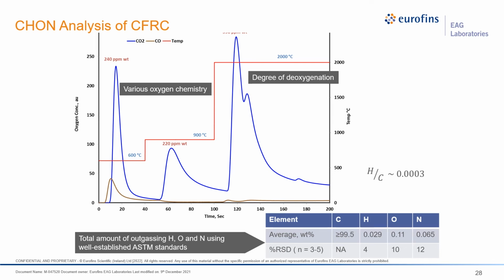On this plot, oxygen concentration in composite is compared with heating time and temperature. The distinct outgassing profiles observed for carbon monoxide and carbon dioxide, two main oxygen-containing species, clearly show presence of different oxygen chemistries and also provide guideline on how deoxygenation occurs for this composite. The table gives concentration of carbon, hydrogen, oxygen, and nitrogen measured using calibration performed by analyzing NIST traceable oxygen standards and also by using ASTM methods. As you can see, we are able to achieve a very good RSD values which enable us to do additional evaluation on this composite by using hydrogen to carbon ratio.